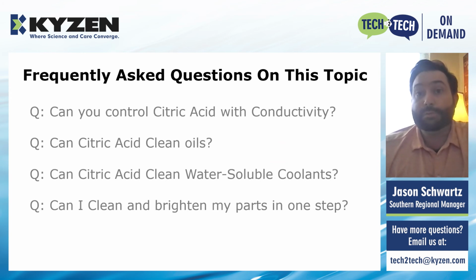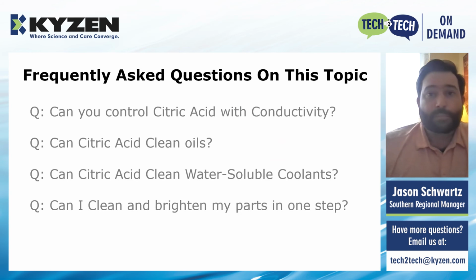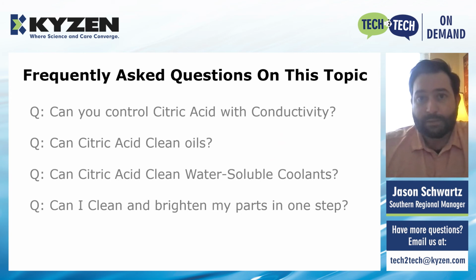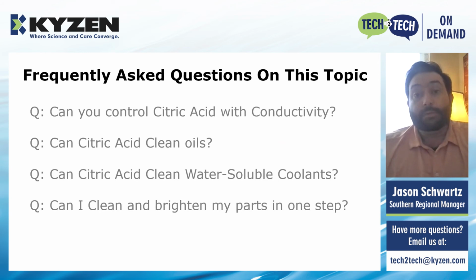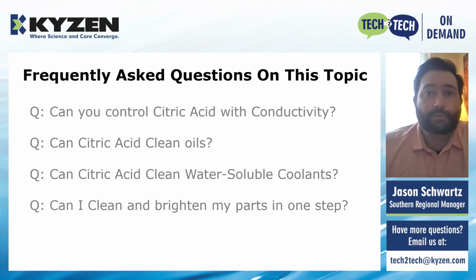pH doesn't have great resolution. The difference between a 3 and a 3.5 on your pH scale can be the difference between 3 and 25% as far as citric acid concentration goes. So that's one of the difficulties with pH. Titration, it's got really good resolution. It's a bit tedious, but it's the generally preferred way to monitor citric acid. There's also some interesting work being done with sonic velocity, but that's kind of a topic for another day.